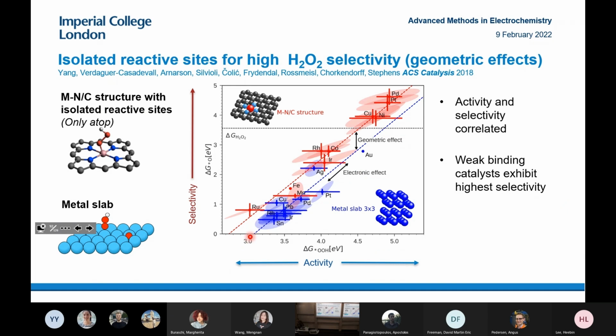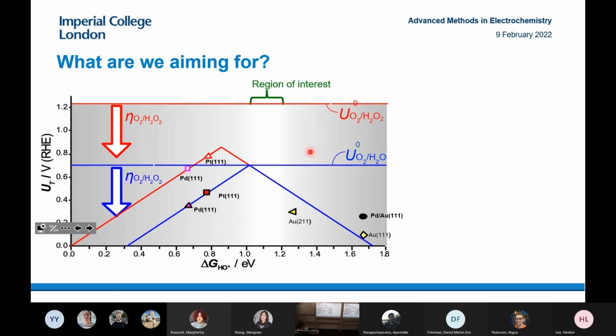and the x-axis is activity. This suggests you can get better activity for the same binding energy on these single atom catalysts. But unfortunately, it also shows that activity and selectivity are correlated. So we thought, what we want to do is make a catalyst with the right binding energy to OH or OOH, which would be around here, and also have a single atom configuration, or a reactive atom surrounded by more inert substrate.